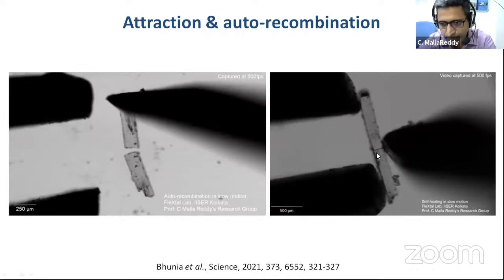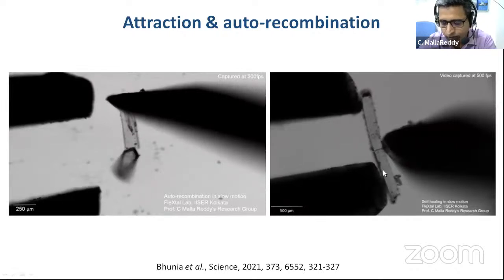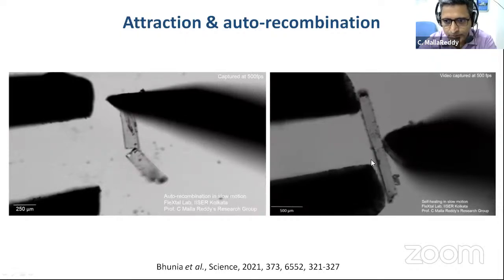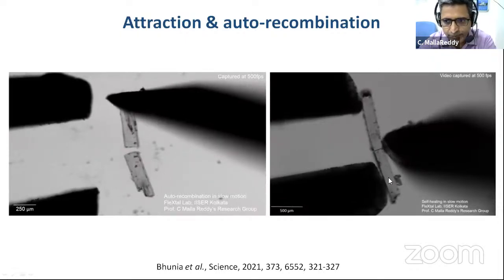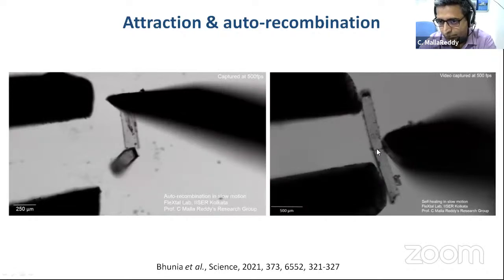And again, as you can see here, healing is perfect, and you don't see anything in the optical microscope. We have also looked under SEM, and under a confocal microscope by doping with some fluorescent materials. So we did not find any crack in cases where you see perfect healing. But there are many cases where perfect healing doesn't happen. For example, if the crack is not linear, or if some debris falls in between, you don't have a good crack.